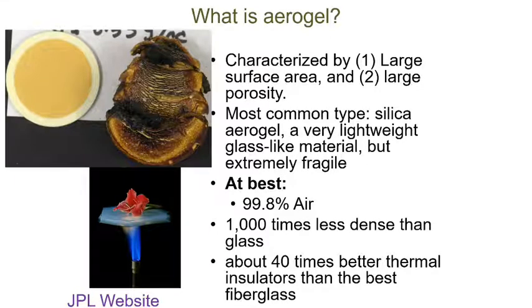Because of that porosity, they can also have some instability in them. So this is a material that I was working with when I was at Oklahoma State. And what happened here is that it's similar to this, but then I touched it with a Dremel tool, and it started burning extremely rapidly and filled almost the whole lab with smoke, and that was not the best night of my life. But you can see that they can have these instabilities in them that you can either take advantage of, or they can cause harm.